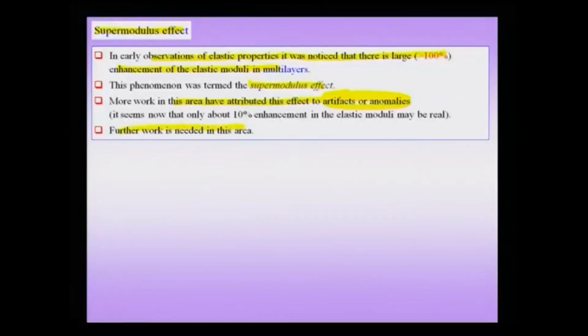These are not perhaps true effects coming from the multi-layer moduli, but there could be other effects coming, and a reasonable assumption perhaps today would be that there is an enhancement in these multi-layers, but that is much smaller than the supermodulus effect which was originally described. But more work has to clarify how general this trend of increment in modulus is, whether it is restricted to multi-layers, or there are other effects which we need to take into account. But clearly the supermodulus effect is no longer attributed as a real effect in nanomaterials, and therefore, it can be ignored.